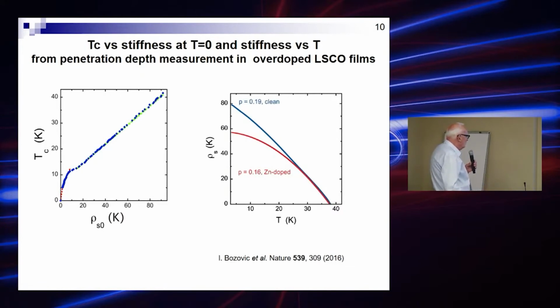linear function of the superconducting stiffness or superfluid density at zero temperature. In clean case and in dirty case, this is when by replacing copper by zinc, the superconductivity is damaged.